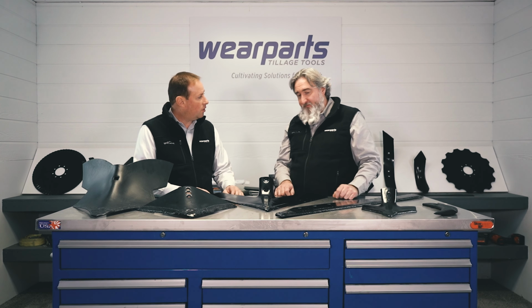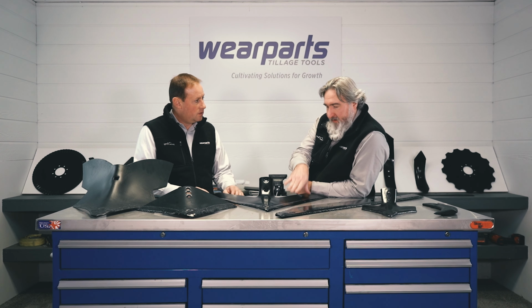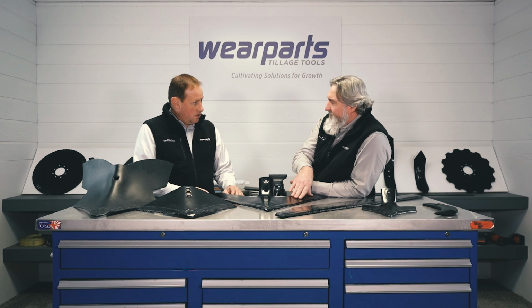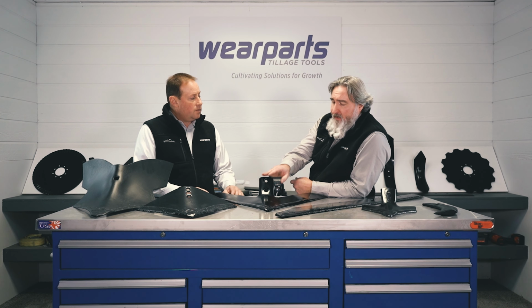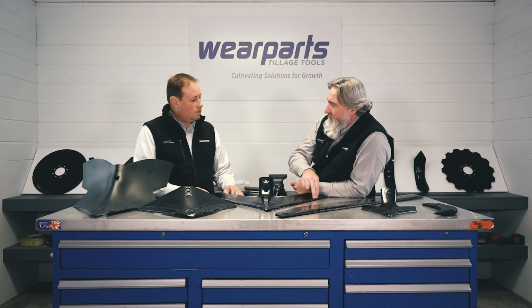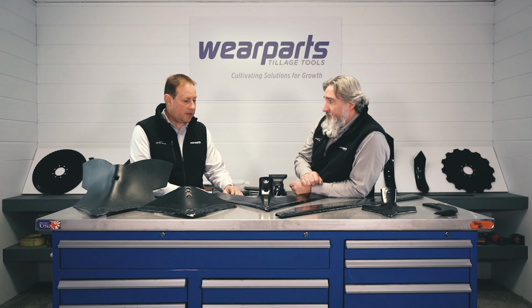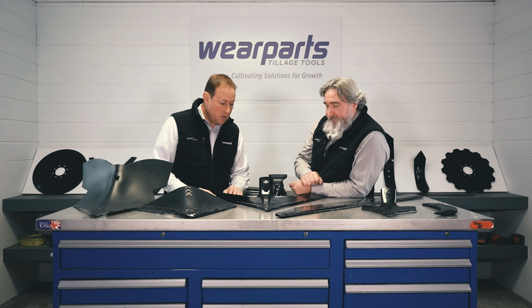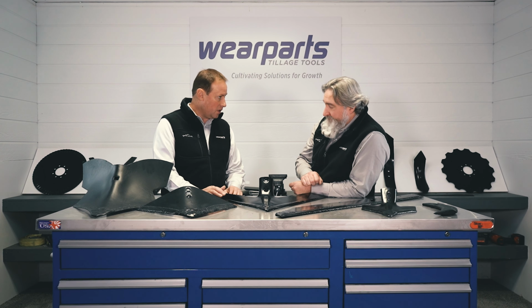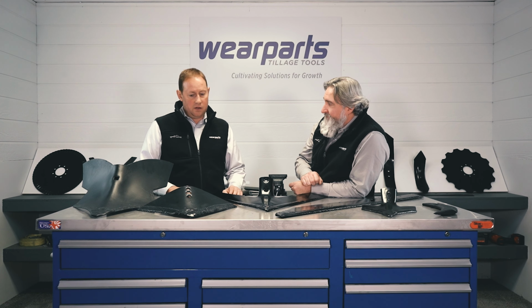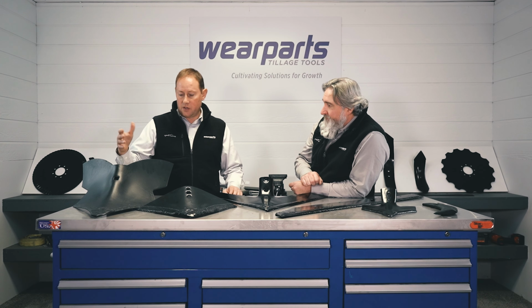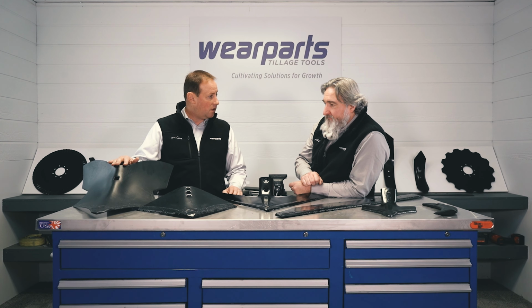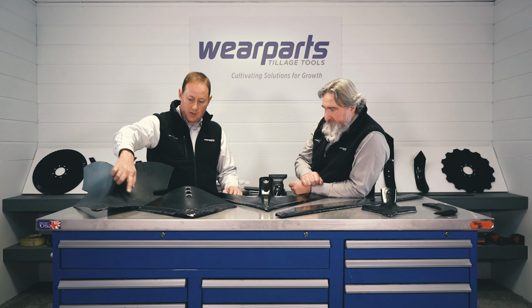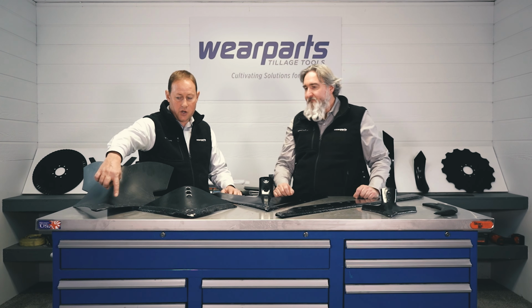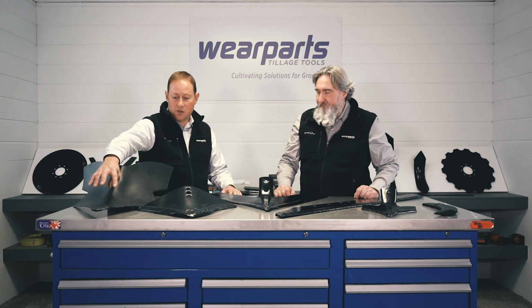So what hardness is this cold metal transfer? If you're looking at a base material here, like 48 to 52 on this heat treated boron, that's pretty high. When we start putting this hard metal on the edge, then you're getting up into the upper 50s. Looking at the specs, it's 58 to 62. So it's actually around 10 Rockwell harder on this edge than the sweep itself. And like I said, here are some examples. This is a big furrower. It's got the cold metal transfer along the edge here, and then it has an oxy-fuel nose because that's such a big nose, you need that heavy-duty oxy-fuel.